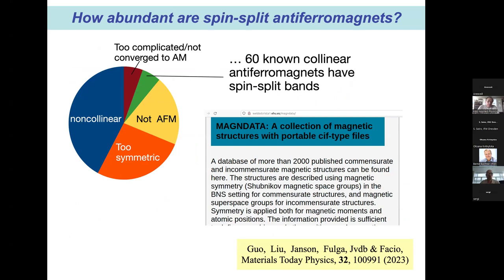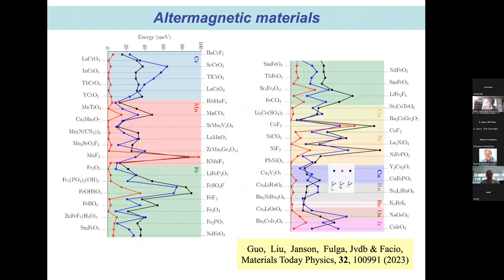In the last 2 minutes, you can ask how abundant are spin split antiferromagnets. We did a calculation considering 2,000 published commensurate structures from the MAGNDATA database, and you can see that a bunch are too symmetric to be altermagnets. Some are non-collinear, which also doesn't count. Some are not antiferromagnets, at least not in our calculations. And then we are left with 60 materials that are collinear antiferromagnets with spin split bands, at least according to our calculations with the FPLO software.